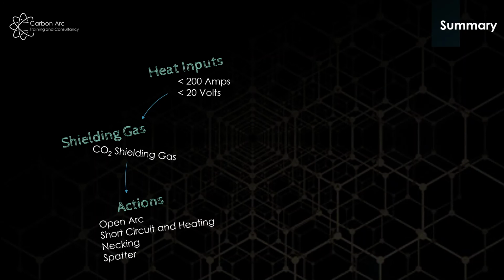What's happening? Well, we've got our open arc, the electrode makes its way through, touches the workpiece, so we get a short circuit, we heat, we get necking, and on breaking we have an amount of spatter. Because overall we have a lower heat input and we're physically touching the electrode to the work we're welding, we can be on thin materials and all position. We're not relying on gravity to pull droplets of weld across the arc.